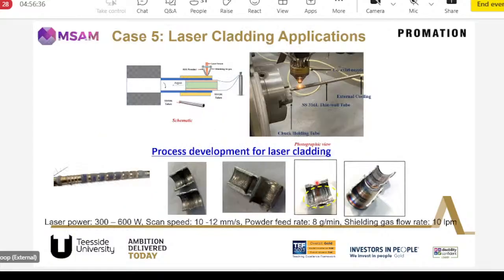This is one of the challenging projects that we did, on laser cladding applications of thin wall tubes for nuclear applications. It's a 0.5 millimeter thin tube, and we use additive manufacturing to create claddings on this. It's really challenging because the tube can get damaged instantaneously when the laser hits the surface. So if you can see the initial trials that we did, the tube was getting punctured at each and every stage when we did the project without any additional steps.